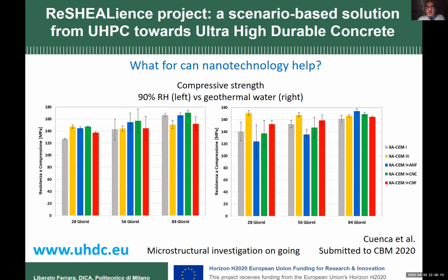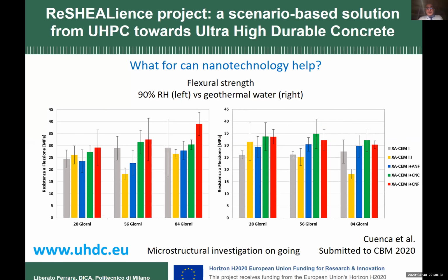The reference mix is the gray column, the blue curve is with alumina nanofibers, and the green and red are with the nanocellulose product. You hardly observe any significant change. But the reason is that compressive strength may not be the performance we should look for. When we look at flexural strength, we really saw an improvement, especially in the long term, and especially in the case of curing under geothermal water.